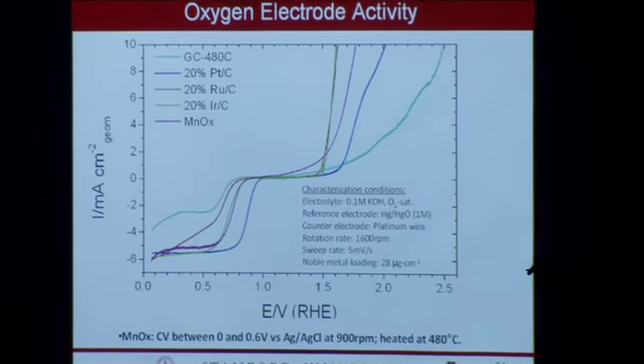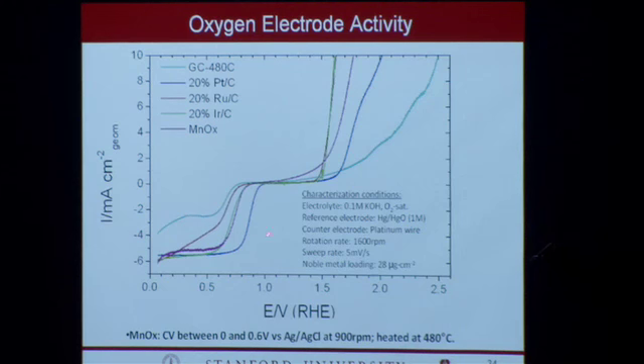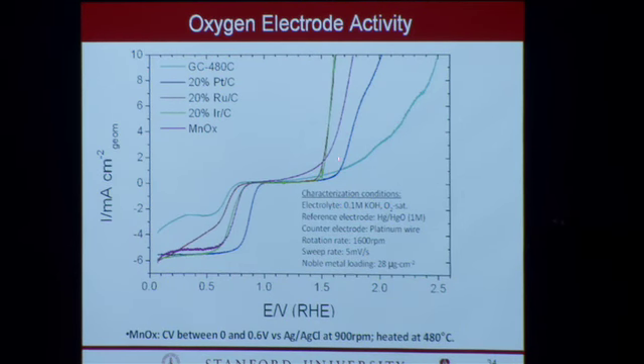These are, again, linear sweep voltammograms, very similar to what you saw before. Oxygen reduction happening here, cross the equilibrium potential, oxygen evolution on this side. And we're going to stack up our manganese oxide catalyst against the best catalysts known in the world: platinum, ruthenium, and iridium. And what you see here is the manganese oxide in pink is, for oxygen reduction, better than ruthenium and iridium and almost as good as platinum, off by just 0.1 volts. What about on the oxygen evolution side? We can see that the manganese oxide, again, is now quite a bit better than platinum, not quite as good as iridium or ruthenium, but again, it's only about 100 or 150 millivolts off.